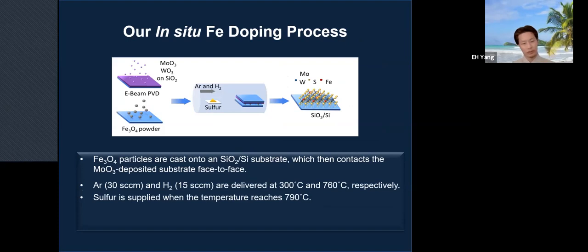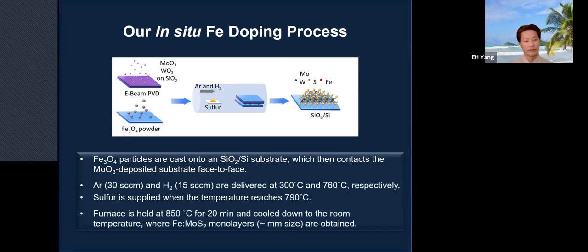And the rest of the procedure is similar, although it's different, and the slight difference makes a lot of effort to tune here. But anyway, in describing, it's kind of simple. So you put argon, hydrogen, at the right time, right temperature, and sulfur supplied at the right time, right temperature. Then the furnace is held at 850 degrees C for 20 minutes before it is cooled down to room temperature, where iron-doped molybdenum disulfide